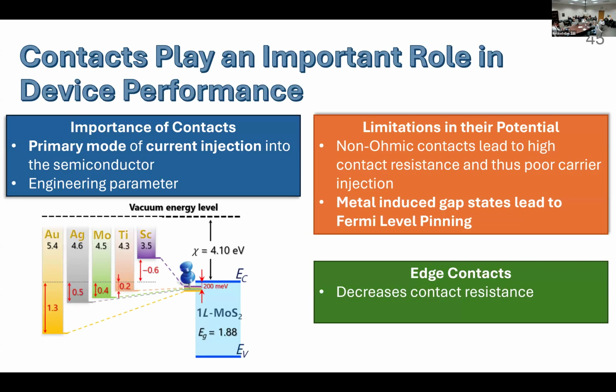So as you might have already gathered, contacts play an important role in device performance. They are the primary mode of carrier injection into our material. They also provide an additional engineering parameter, so we can choose to selectively or preferentially conduct holes or electrons depending on the type of metal that we use. However, this is just in theory. In actuality, these deposition processes induce defects into our materials, which can introduce trap levels within the band gap that do not allow us to tune the Fermi level as freely as we wish.